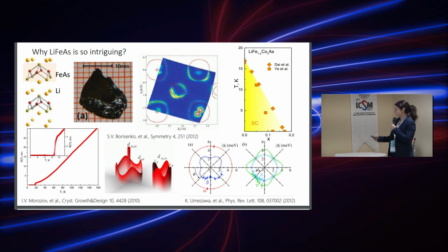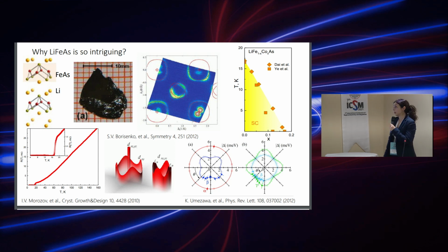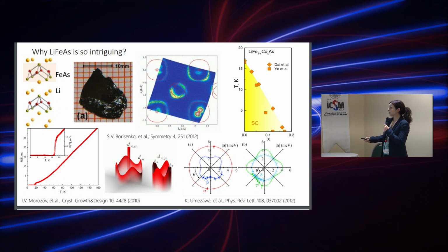Lithium iron arsenide superconducts in the stoichiometrical state and shows its optimal critical temperature in this state, about 18 kelvins. And any doping or lithium deficiency effectively decreases the critical temperature. So this phase diagram resembles that of magnesium diboride. Several ARPES studies show the Fermi surface of lithium iron arsenide and the presence of several superconducting condensates below the Tc with a strongly anisotropic superconducting order parameter.